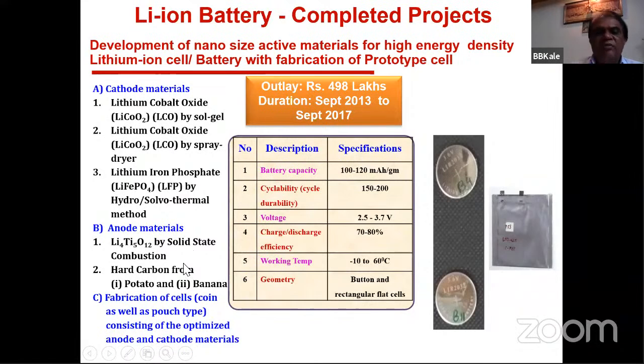Then we started working on biomass like potato and banana and some other biomass and made carbon out of it. So we made a porous carbon, a mesoporous carbon, and a graphene-like structure. Graphene has holes, porous graphene, you can see, some 20 nanometer, 30 nanometer holes. Deliberately we did that for good porosity.